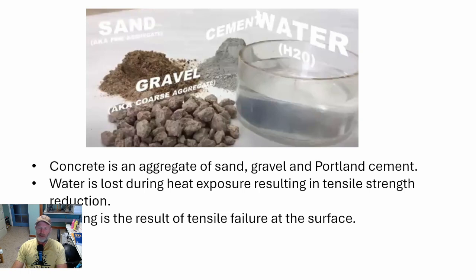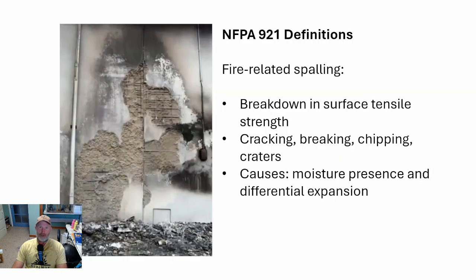To understand spalling, the first step is to understand what concrete is. Concrete is an aggregate: basically 1 part Portland cement, 5 parts other stuff. The other stuff is sand and gravel. During exposure, water is lost because of evaporation, both from the crystalline structure of the Portland cement as well as the aggregate. That lowers the tensile strength of the material. So spalling on concrete is the result of tensile failure at the surface.